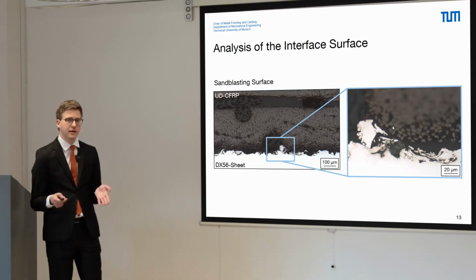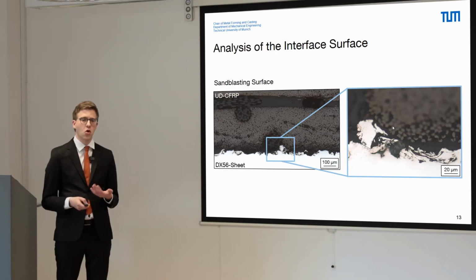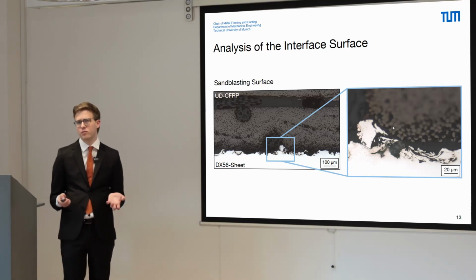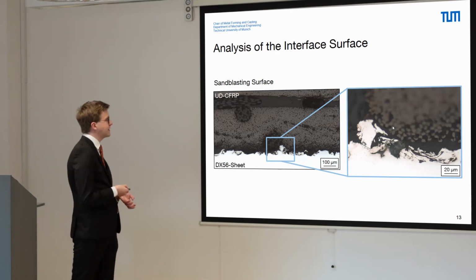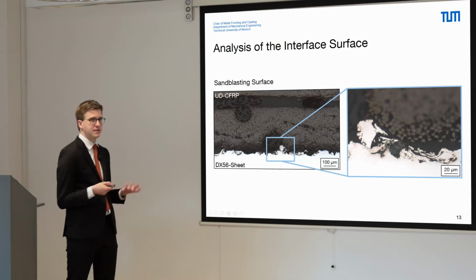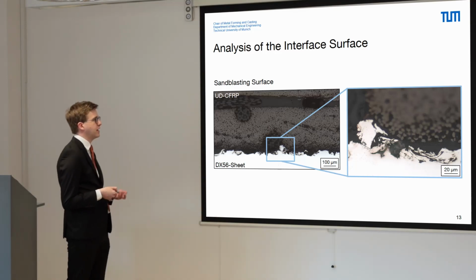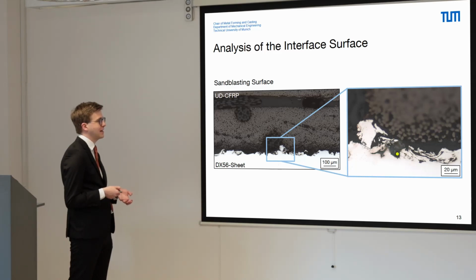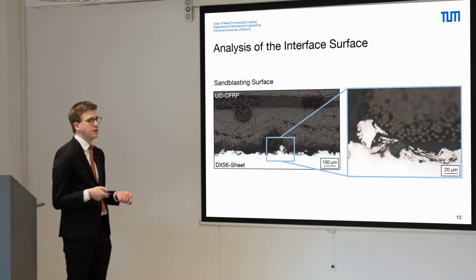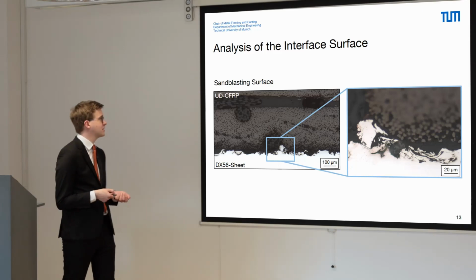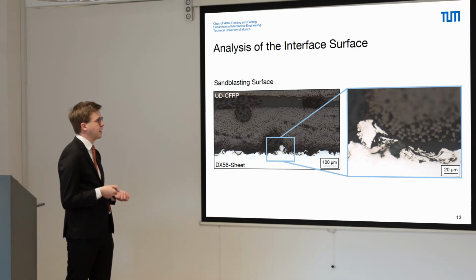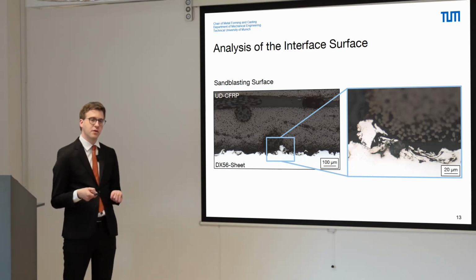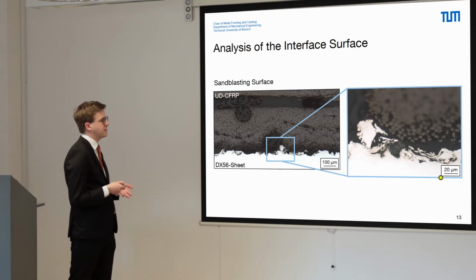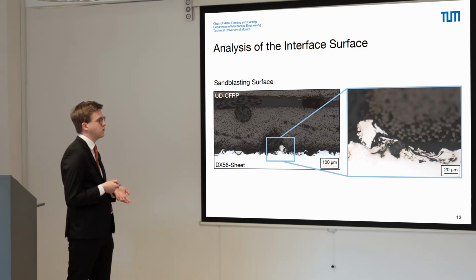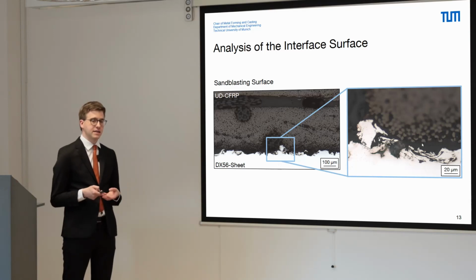But not only the cross-section of the composite is of importance, also the interface due to the possible problem of delamination. And here we can see that, as the mechanical adhesion theory has predicted, we were able to manufacture microscopic undercuts in which the matrix resin can flow and therefore form sufficient bond strength for our further experimental investigations for the sandblasting structure here. And as we already saw in the previous microscopic images, it's more of a hard-edged and irregular surface structure due to the impact of the blasting particles.